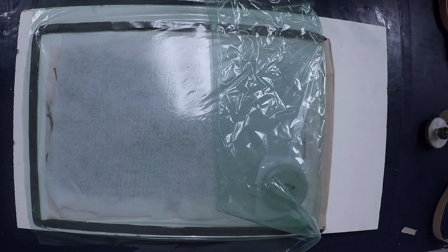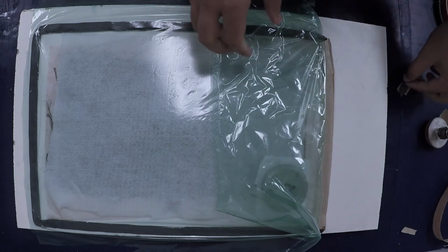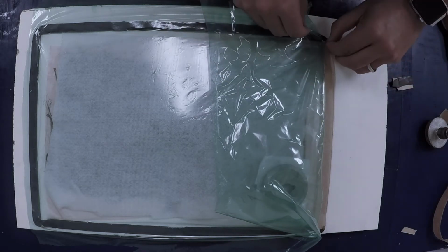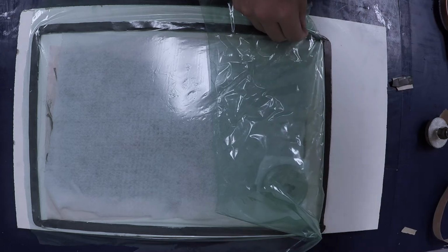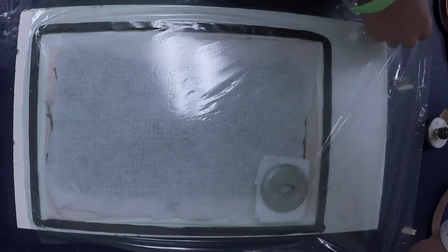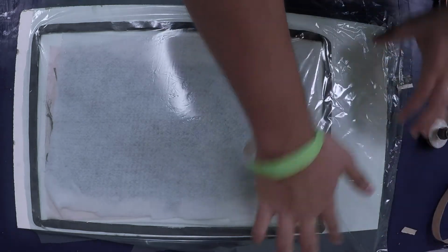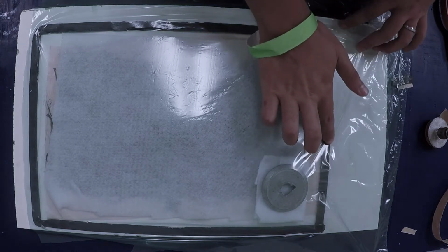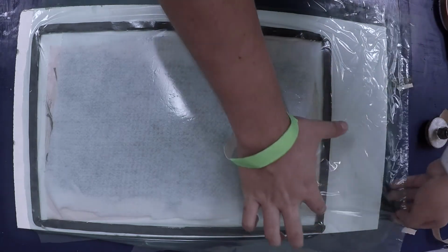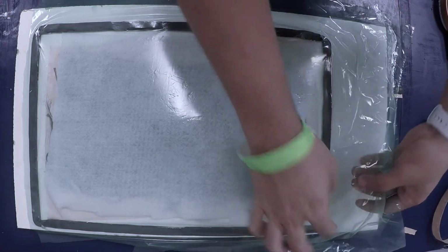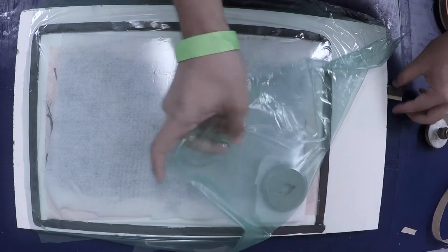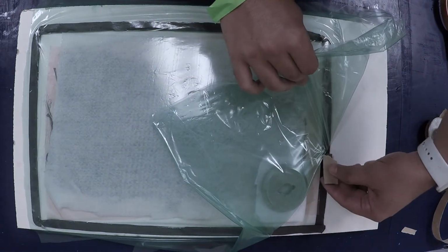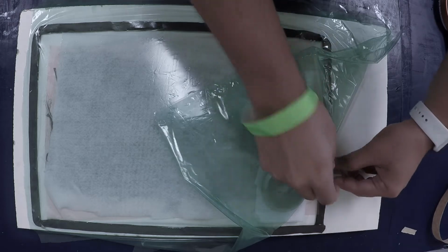During this process, have a few short strands of tacky tape ready. This is in case you need to form any cleats. As you can see, my last side has a longer bag than the available tape. To get the bag to fit properly around the mold, a cleat must be placed. This is done by placing the short strand of tacky tape on top of the tacky tape that is already present, to form a vertical portion of the seal.